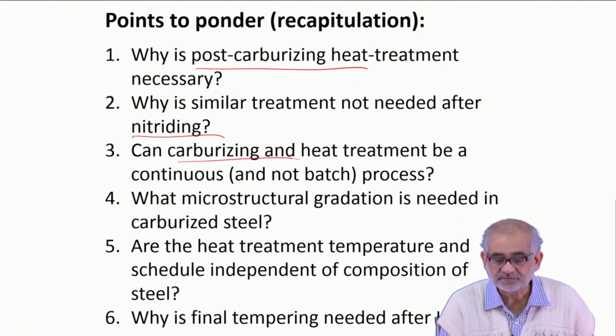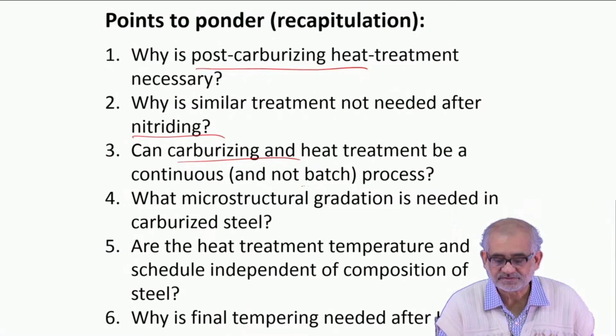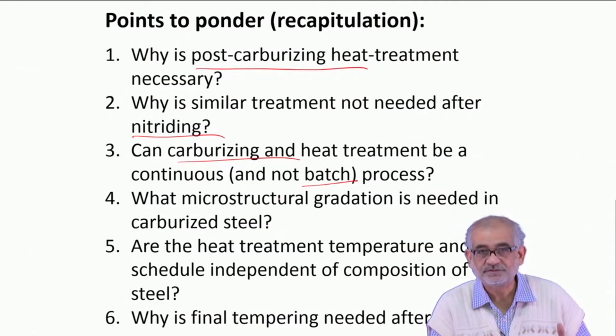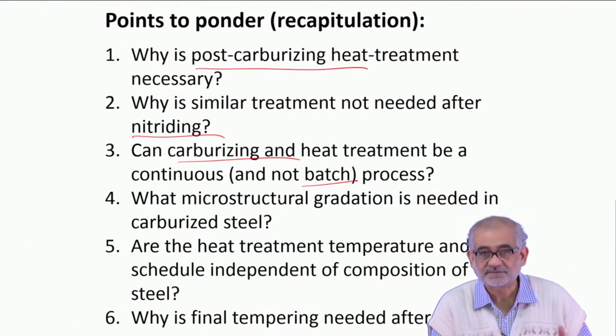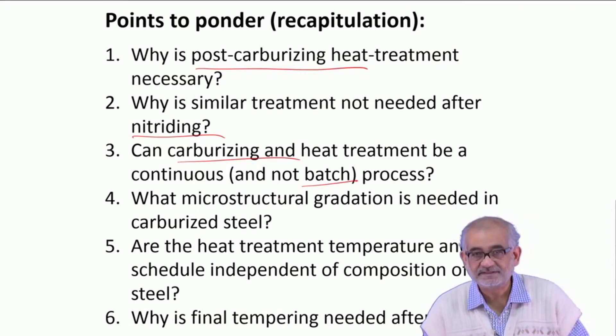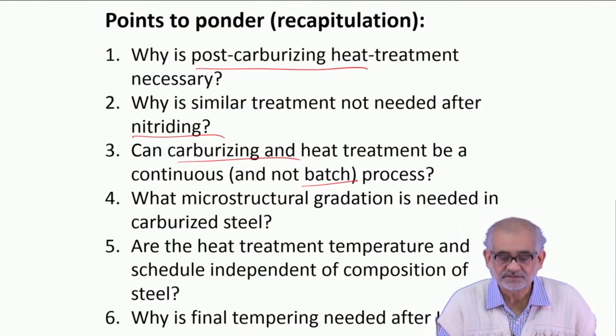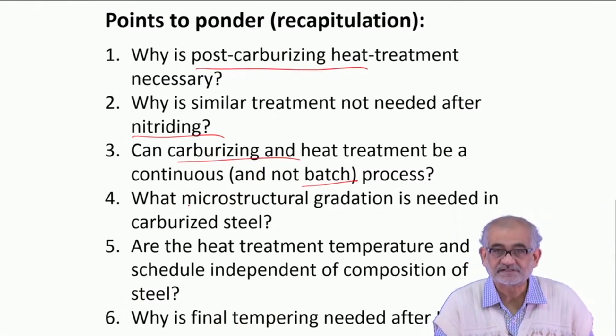The carburizing treatment unfortunately is a batch process, not a continuous process, because you need to break the carbon-rich atmosphere and then take it out and carry out the heat treatment. It cannot be a continuous process except in very rare cases of some gas carburizing treatments.